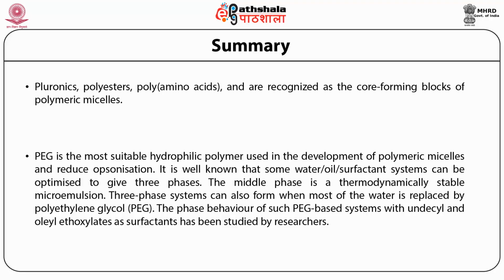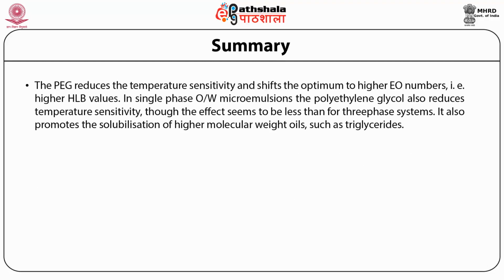It is well known that some water-oil-surfactant systems can be optimized to give three phases. The middle phase is a thermodynamically stable microemulsion. A three-phase system can also form when most of the water is replaced by polyethylene glycol. The phase behavior of such PEG-based systems with undecyl and oleyl ethoxylates as surfactant has been studied by researchers. The PEG reduces the temperature sensitivity and shifts the optimum to higher EO numbers, that is, higher HLB values. In a single-phase oil-in-water microemulsion, the polyethylene glycol also reduces the temperature sensitivity, though the effect seems to be less than for the three-phase system. It also promotes the solubilization of higher molecular weight oils such as triglycerides.